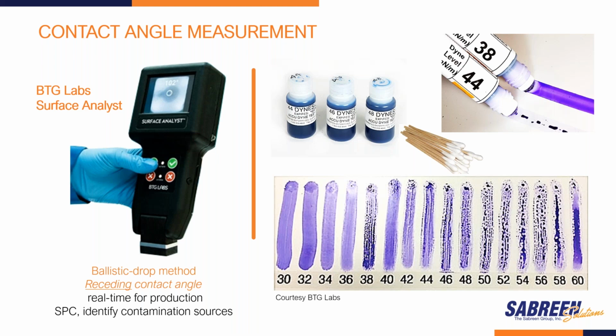After we've pretreated a surface, which is time dependent, it takes some time for low molecular weight oxidized materials to settle. So we want to avoid dyne pens whenever we can. The good news is that BTG Labs has invented and come out with their Surface Analyst, and it completely eliminates the need for dyne pens, and this is where industry needs to go. This is a ballistic drop method in which several drops of distilled water are shot onto a surface, and virtually instantaneously you're able to see what that contact angle is. I'm not going to get into all of the details about advancing and receding contact angles, but this system does an exceptionally good job of reading the receding contact angle, which is what we're most interested in, the high energy components.